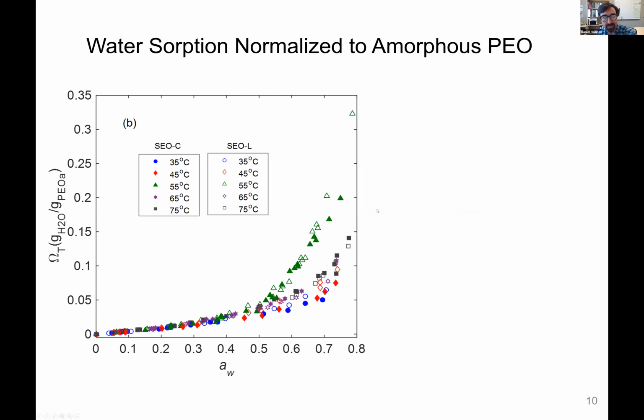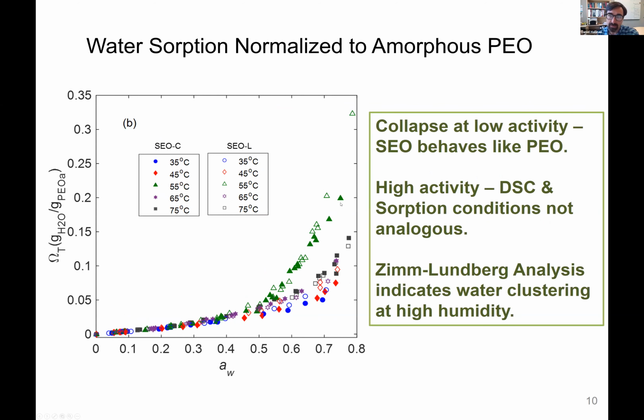We don't get the collapse at high activity, and really we think the reason for that is that our measurement of crystallinity and our measurement of absorption isotherms are not analogous. Really, the degree of crystallinity has a lot of uncertainty because of just limitations of the measurement that I won't go into due to time limitations.